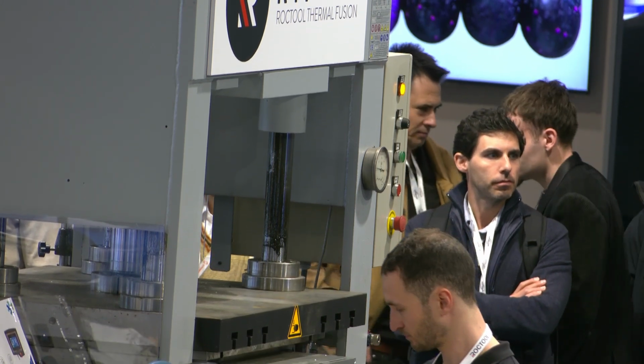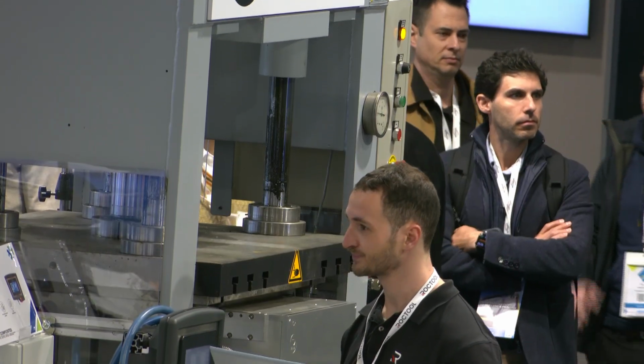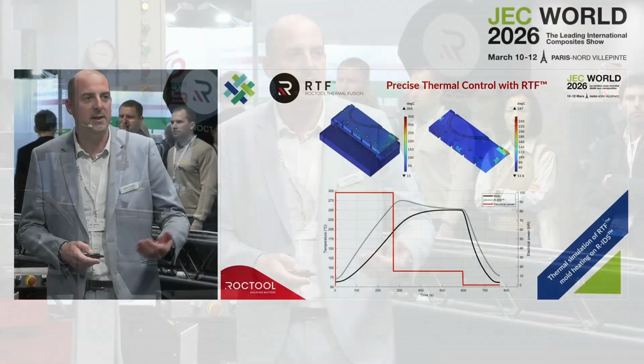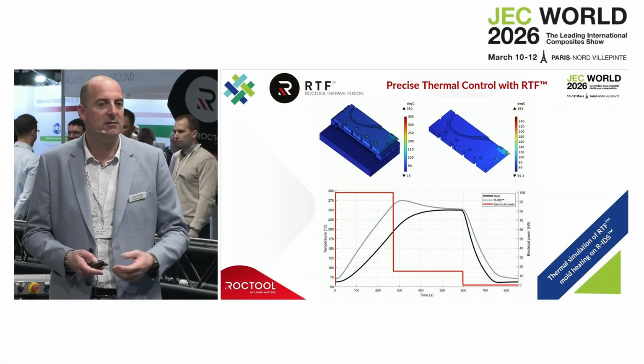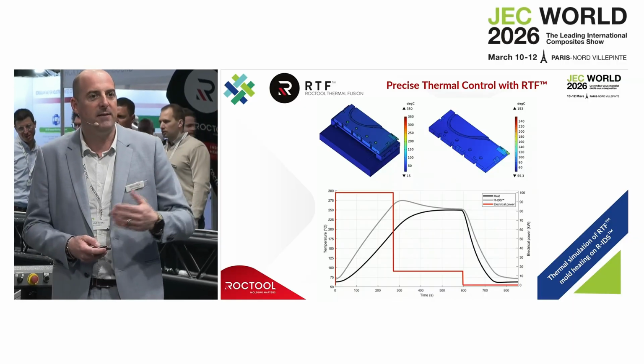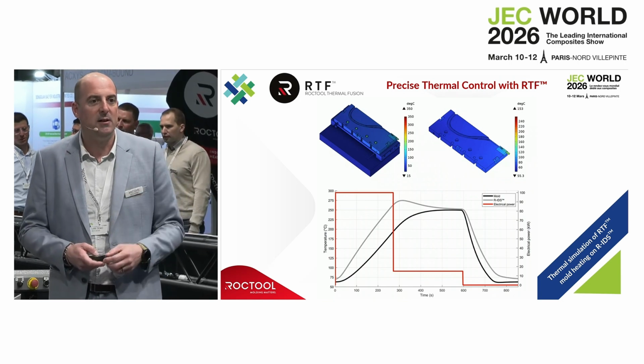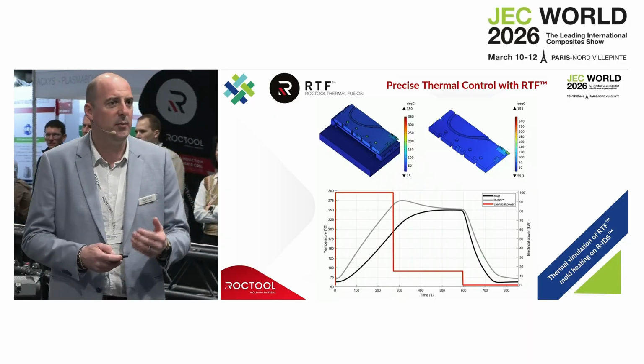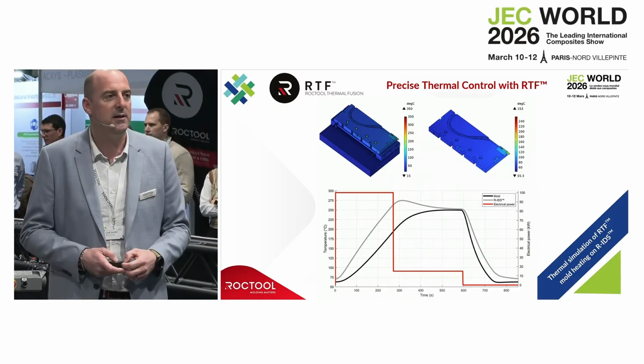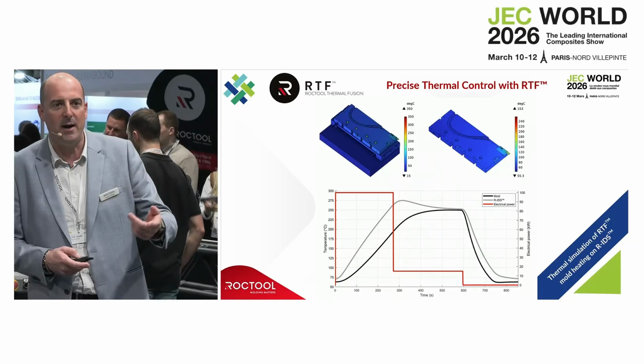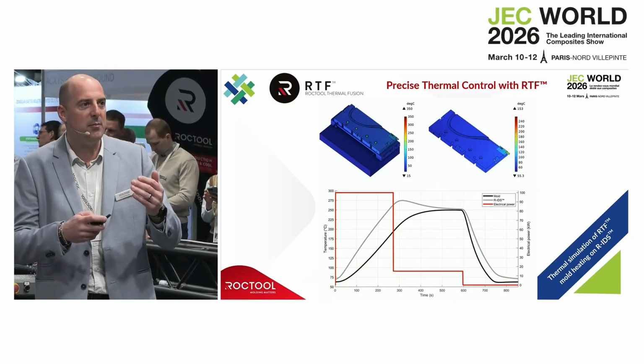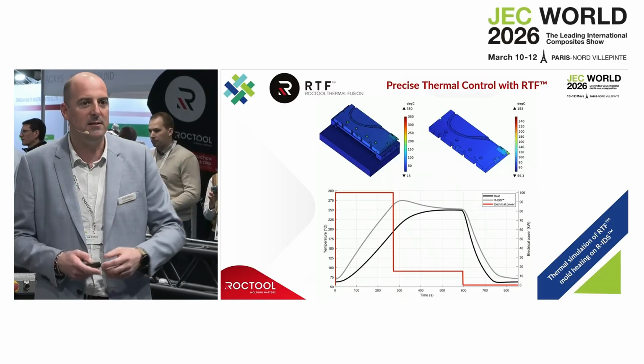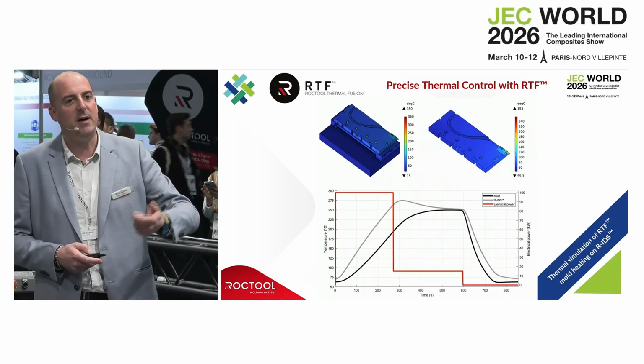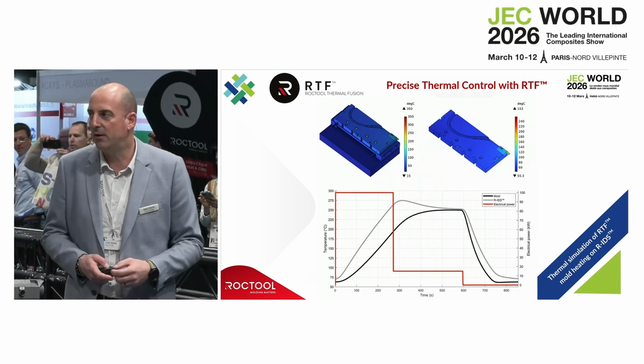One important know-how of Roctool is also to be able to make advanced engineering study to define the performance of the solution. So in this information that we share with you, we are able to define the temperature behaviors of the process during the heating, the holding, and the cooling with thermal simulation. So as you see on the slide, we can define in advance the heating ramp. And as you see, we can also control a different temperature and different heating performance between our heat and cool platen and on the insert mold. That's the two different curves that you have in black and in gray. And you can see that we can have a gap between the reeds, which is our heat and cool platen, and the insert mold to be able to optimize the heating ramp. So that's the view of what you have in front of you.